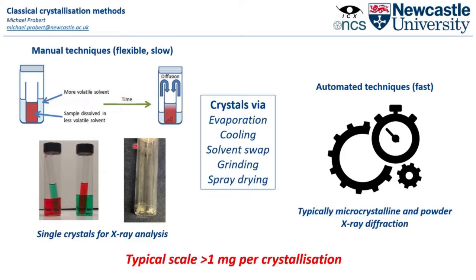They are incredibly flexible, but the amount of time commitment from the researcher is huge. So this is problematic if we're using this to explore crystallization space, particularly when the amount of material per crystallization experiment might be quite large. So we have some issues there that we need to be aware of, particularly if we're in a sample limited condition. There are some automated techniques which take these manual approaches and just speed them up a little bit. They are less flexible, require actually larger amounts of material, and generally give back microcrystalline and powder samples rather than the single crystals that we would like for full analysis.